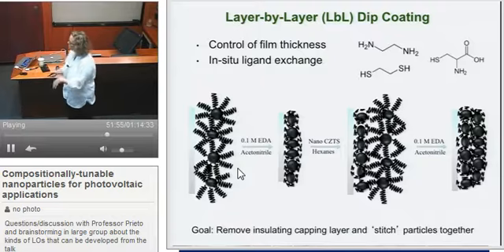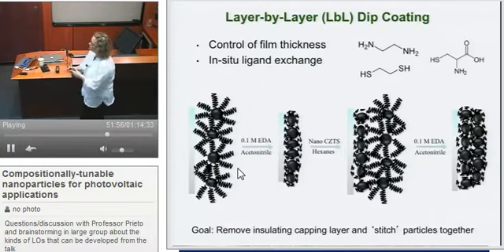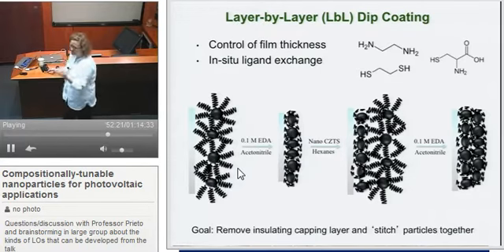So in this case, we want to make a thin film. We have these nanoparticles with the organic surfactant, but they are really insulating, these long-chain organic molecules. So we need to get them off. What we do is take our transparent conducting electrode, which is going to be our current collector, and dip it in our nanoparticle ink so we get a thin layer. I don't mean to imply it's a monolayer. It really isn't single layer nanoparticles. I just mean to say it's thin.